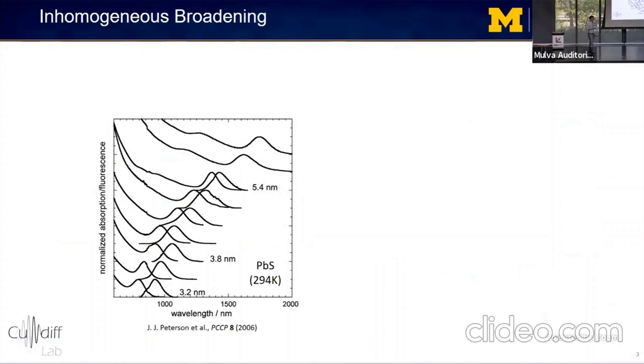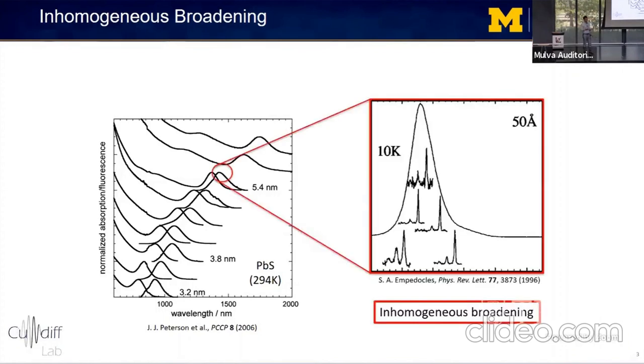So for example, here's absorption and fluorescence spectra of lead sulfide nanocrystals, where you can see red-shifting absorption and fluorescence with increasing nanocrystal size. What I want to point out, though, is that these peaks just look like broad Gaussians without any obvious structure on them. But if we compare the fluorescence of an ensemble to that of individual nanocrystals, you can see that these broad Gaussians are actually composed of narrower line shapes from individual nanocrystals. And this shows that inhomogeneous broadening dominates the linear optical properties of an ensemble.